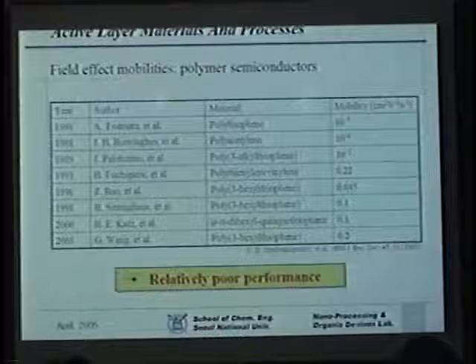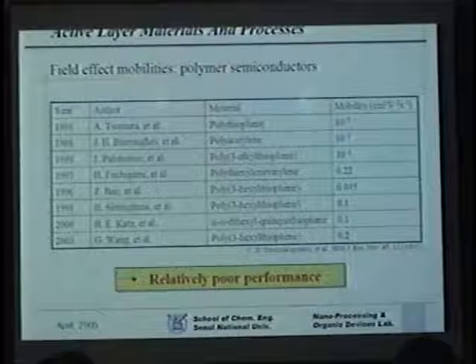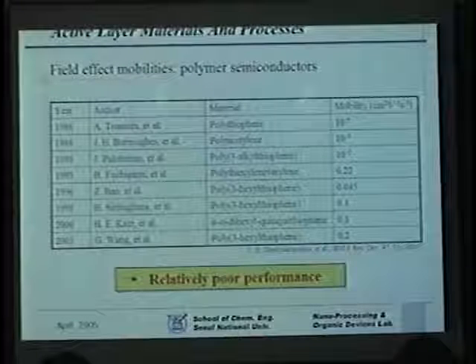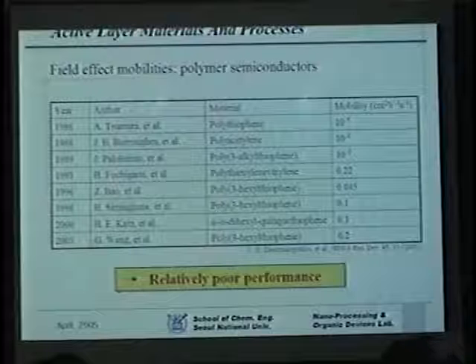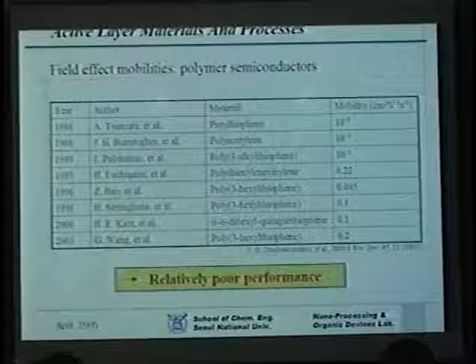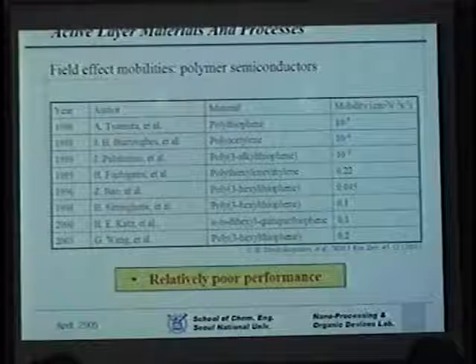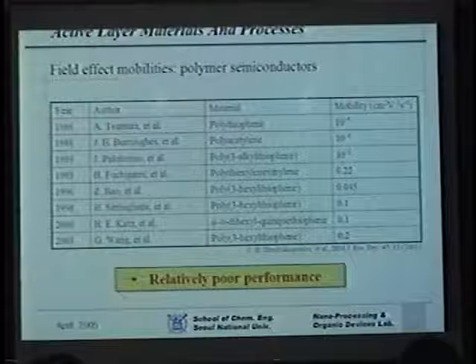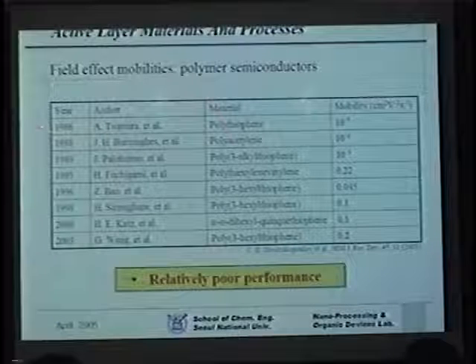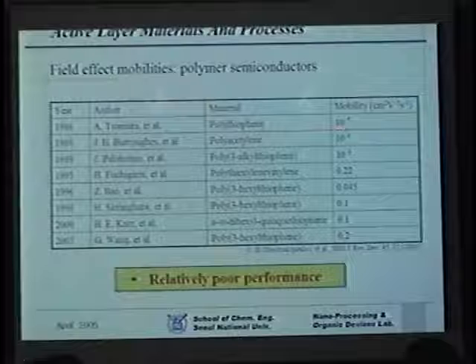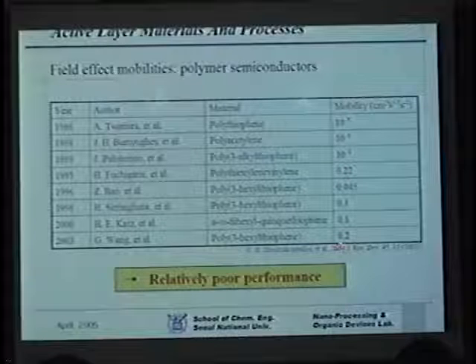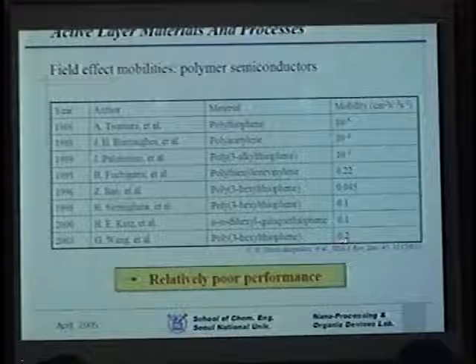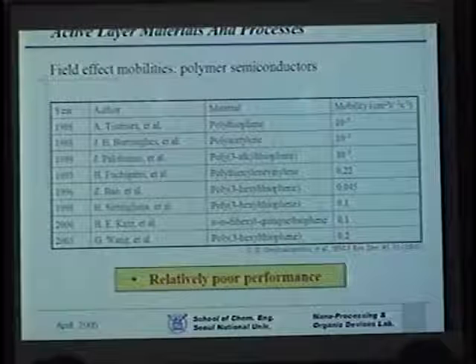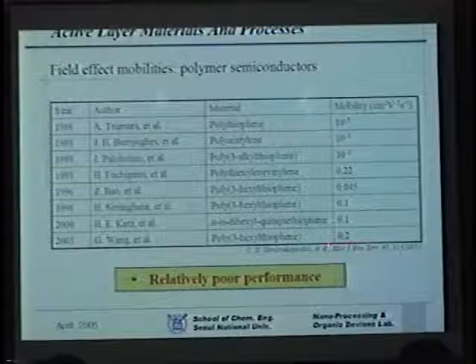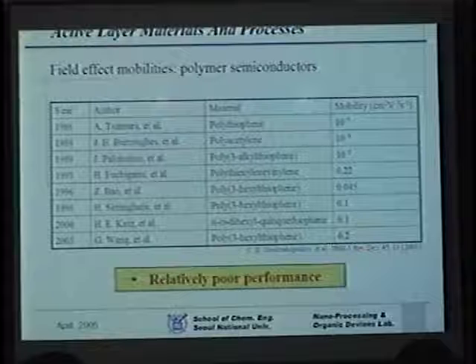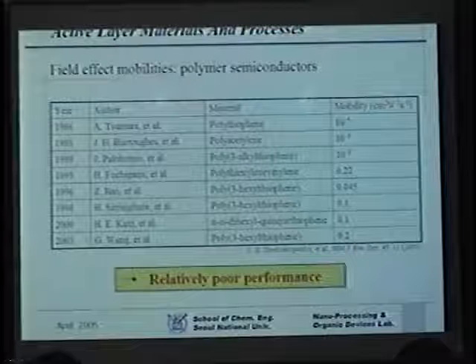But when it comes to polymer semiconductors, that is not the monomolecular organic but rather polymer, the performance gets fairly bad. 10 to the minus 5. Although there has been an improvement of the order of, say, about 4 orders of magnitude, it is still about an order of magnitude smaller than organic, the pentacene, for instance.